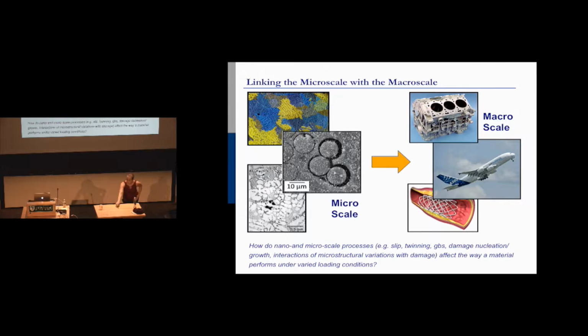However, if you were just looking at this, this is a silicon carbide matrix, and this is a silicon carbide fiber. If you just had the matrix, if you just had the silicon carbide, your material would be very, very strong, but very, very brittle, and it would be useless in a plane. You would not want to fly in a plane with that as a turbine blade, because the minute you had any sort of impact, no turbine blade.